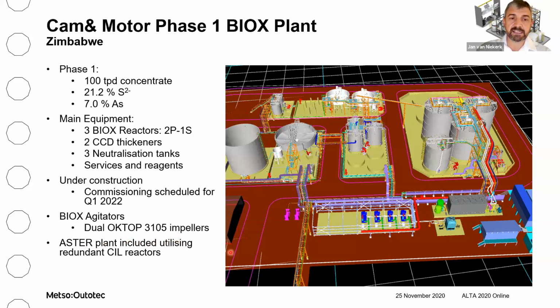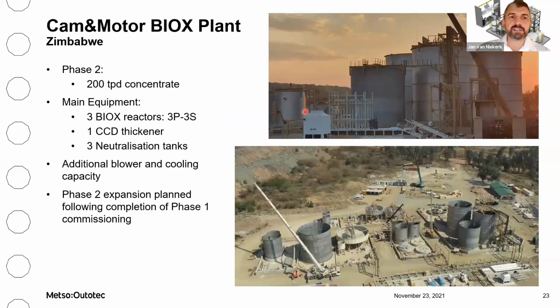The plant will also include an ASTER plant using some redundant equipment for thiocyanate destruction. Phase 2 will then expand the capacity to 200 tonnes per day of concentrate with the addition of 3 additional BIOX reactors, 1 additional CCD thickener, 3 neutralization tanks. Additional blower and cooling capacity will also be added as part of the expansion. And here you can see a fairly recent photograph of the construction site showing the 3 BIOX tanks with the BIOX stock tank, the 2 CCD thickeners and the 3 neutralization tanks, as well as some water tanks and the tailings thickener.